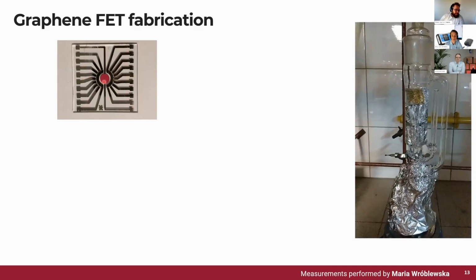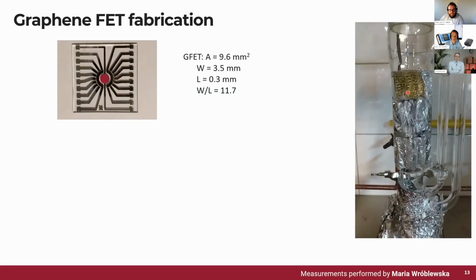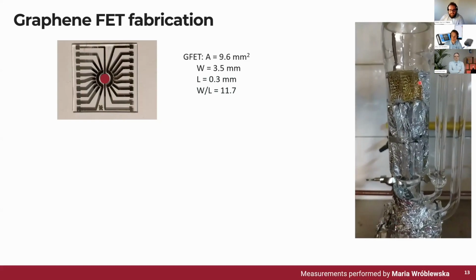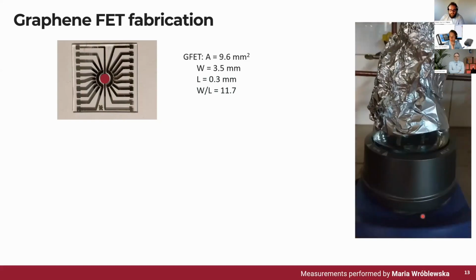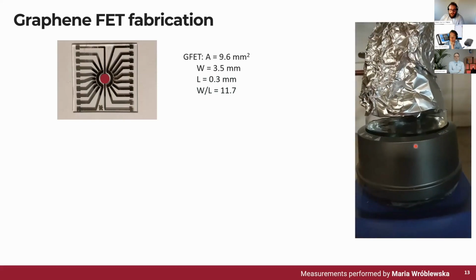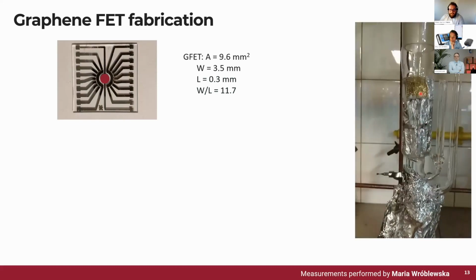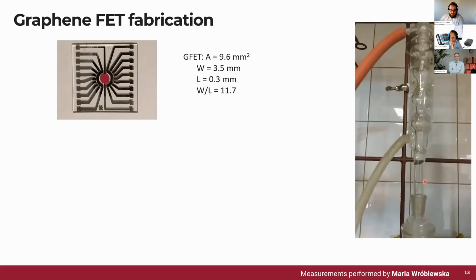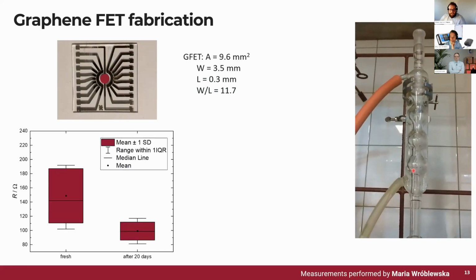Now I'm using just those two, which gives me a GFET of about 9.6 millimeters square with a width to length ratio of about 12. And what you can see in here is the Soxhlet extraction process, where I clean the graphene of PMMA traces. This is done in a Soxhlet extractor so that the graphene is constantly cleaned with